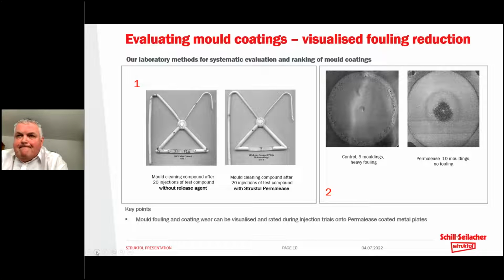On the right-hand side, method 2, we can really assess, looking in more detail at the surface of the plate, the durability of the coating. So we look at the right part of method 2, Permalease 10, one of our earlier coatings. We see no sign of any particular fouling. We can see the extent of the mold fouling, the mold flow, if you like, in a radial disc, and a slight degree of wear in the center.